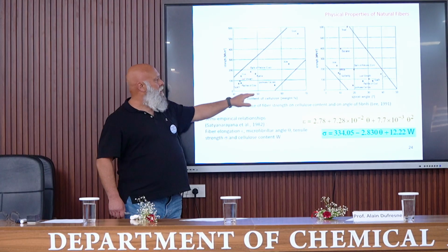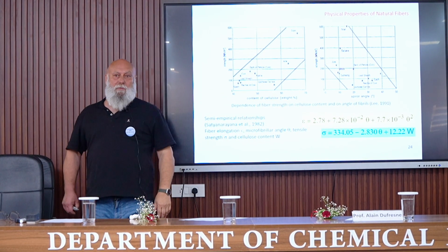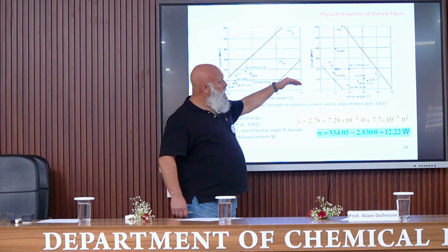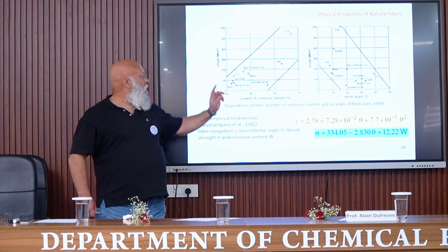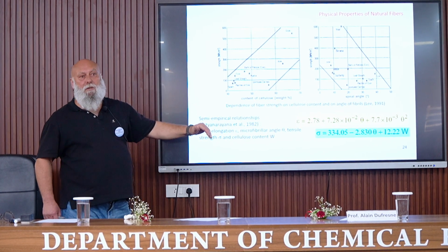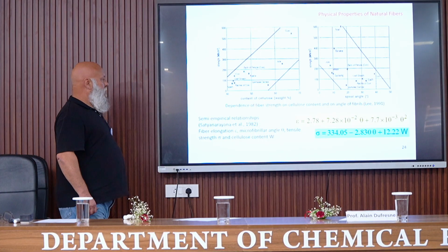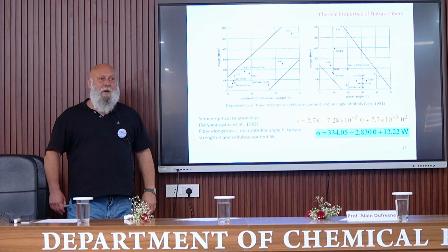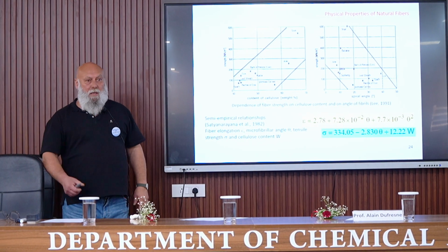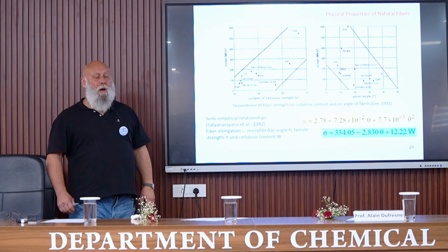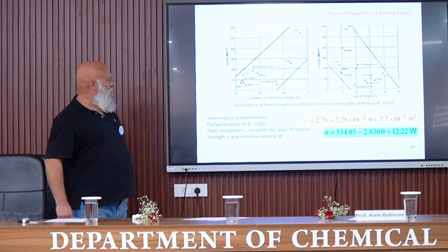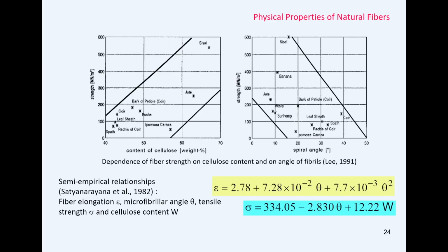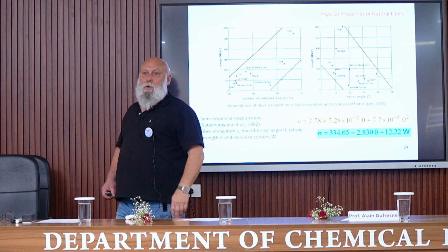When increasing the cellulose content, we observe an increase in the strength of the fiber, and when increasing the spiral angle, we observe a decrease in the strength of the material. So it means that to have efficient natural fibers, it's necessary to have a high cellulose content and a low microfibrillar angle. So some equations have been proposed to determine the strength of the fiber and the elongation at break as a function of theta, which is this microfibrillar angle, and W, that represents the cellulose content.